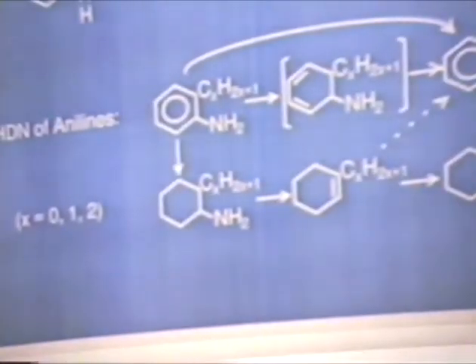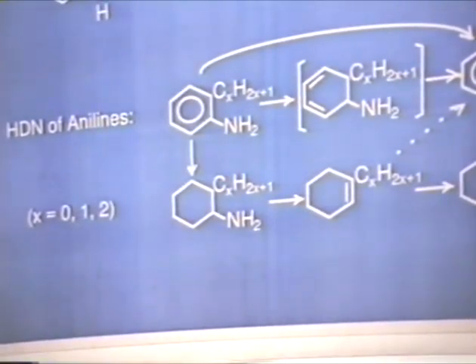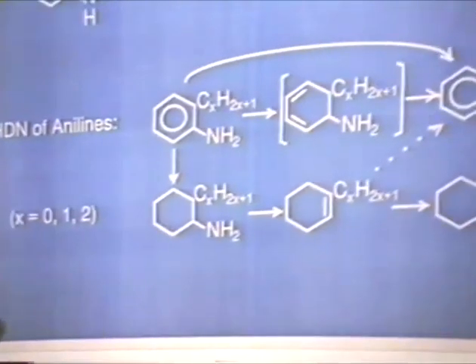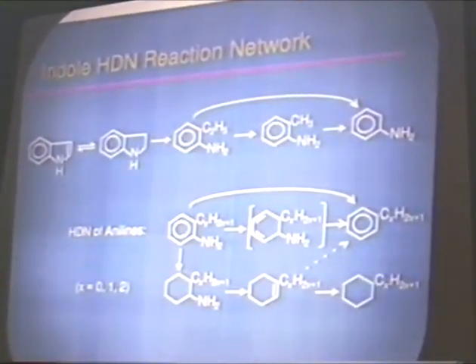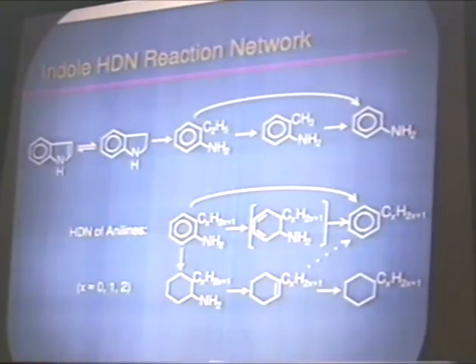Now, if we move on to the indole HDN reaction network, again, based on our observations as well as some of the reports from the literature, the working mechanism that we are proposing consists of an initial step, which is usually thermodynamically controlled. It is a readily reversible hydrogenation of the heteroatom, resulting in indoline formation, followed by the first hydrogenolysis step, giving us